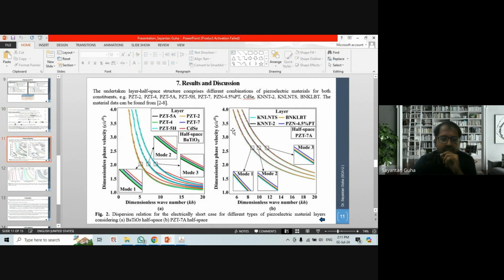So when I chose these combinations, I found out the velocities of each and every layer. I found out the velocity of the half space, and I ensured CL is less than CH. After that, I was able to solve the entire problem. You can take any other combination, but always keep in mind that the CL less than C less than CH condition has to be satisfied. Otherwise, the Love wave is not going to propagate.